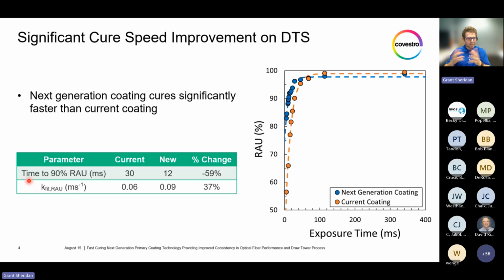Shown here as a benchmark, we looked at the time to 90% cure, 90% RAU, which we felt was a good number that was achieved on actual draw tower processes and manufacturing. So as we can see here, this new generation technology decreased the time by about 60%, from 30 milliseconds all the way down to 12 milliseconds. Furthermore, from the pseudo first order kinetic fit, we're able to extract a reaction rate constant. And we can see that this next generation coating improved this about 40%.